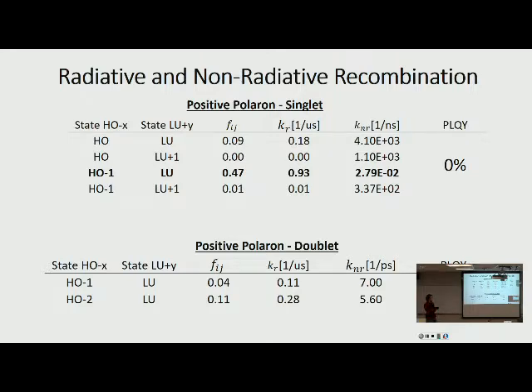I've been trying to think of a mathematical model to be able to scale radiative and non-radiative rates based on energy transitions. But I haven't come up with a good model yet to predict what would be good emitters and what wouldn't be, just based on energy differences and couplings or orbital overlaps, basically. But just from one system, radiative varies between these low energy transitions, 1 order of magnitude, and now non-radiative is 5 or 6 orders of magnitude, just from HOMO -1 to LUMO.